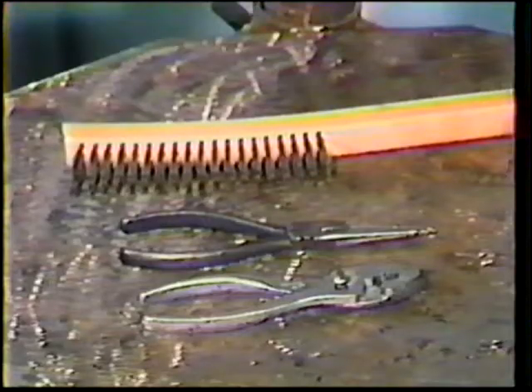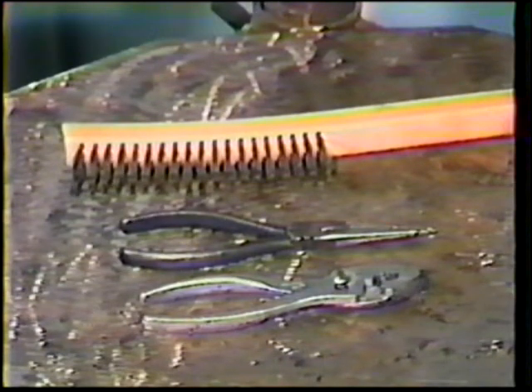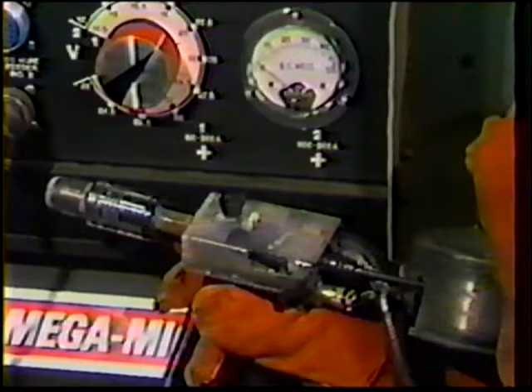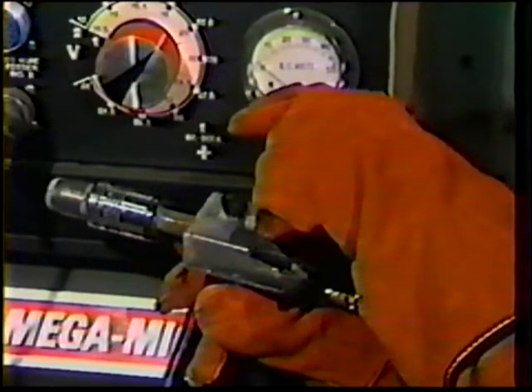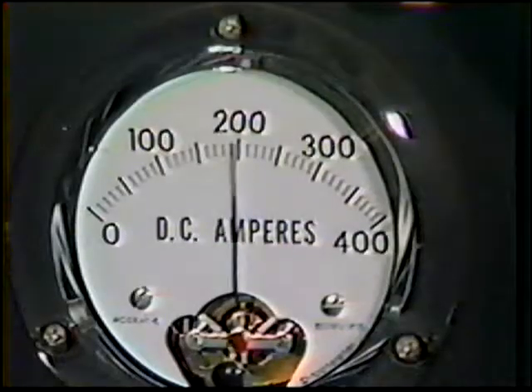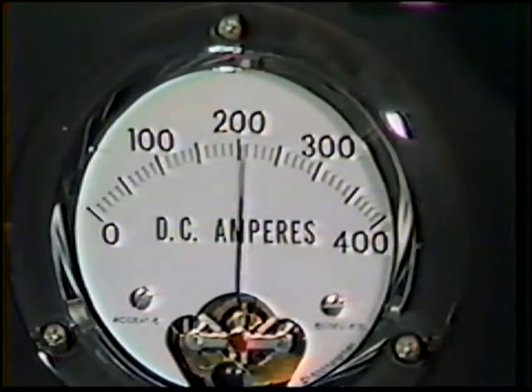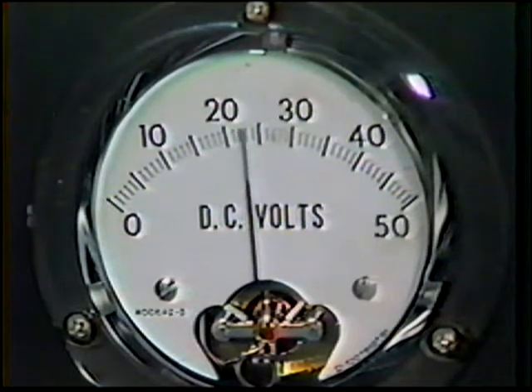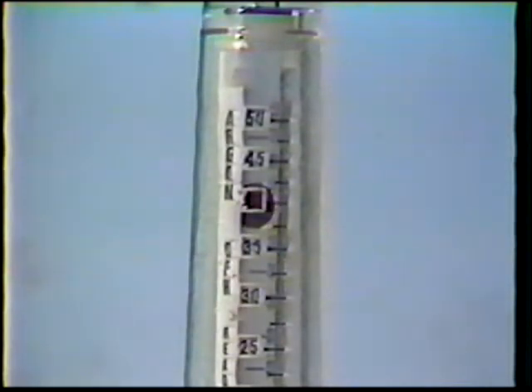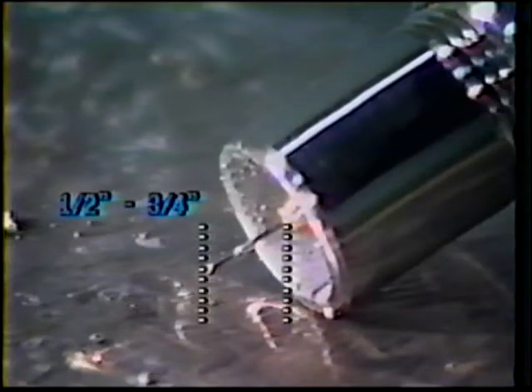The equipment is the same as previous job practices, including protective clothing, gloves and helmet, and stainless steel wire brush, wire cutters, and pliers. For the machine settings, the polarity remains direct current electrode positive, or reverse polarity. The amperage setting is increased to a range of 195 to 205 amps, and the voltage range is increased to 22 to 25 volts. The gas flow rate is set to 40 cubic feet per hour. And the electrode wire stickout will range from 1/2 to 3/4 of an inch.